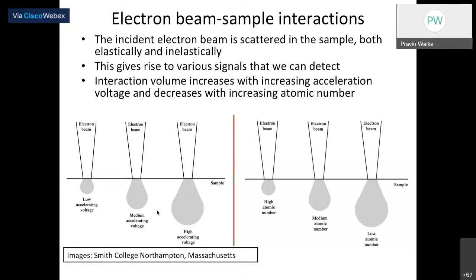So once this electron beam interacts with the sample, we can get various signals, right? The volume of the interaction here will be drastically increased with respect to accelerating voltage. But on the other side, the interaction volume of that particular beam will simultaneously decrease with increasing atomic number of that material specimen. The specimen uses some sort of atoms, and what are the atomic numbers? If your atomic number goes on increasing, then definitely the interaction volume goes on decreasing, right?